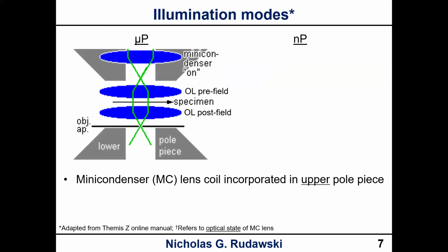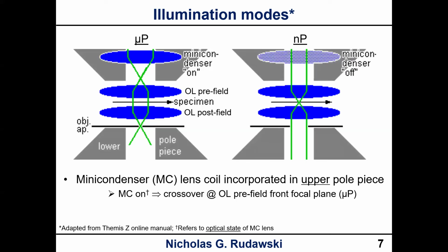So based on this, we can define two illumination modes. Another aspect of the twin lens design is that you have what's called a mini condenser lens that is incorporated into the upper pole piece, specifically a lens coil. Okay. So when you turn the mini condenser lens on, you introduce another crossover in the beam path that is about at the front focal plane of the objective lens pre-field. That gives you broad, mostly parallel illumination. Okay. That's what we call microprobe mode.